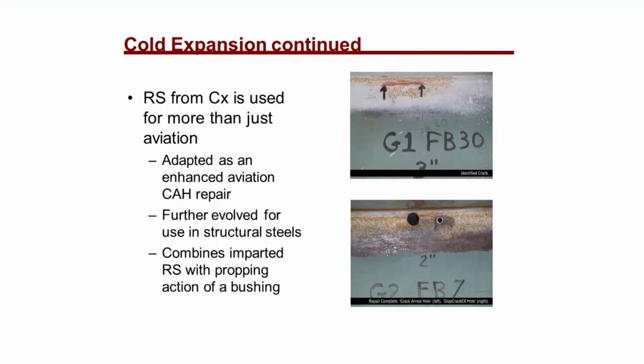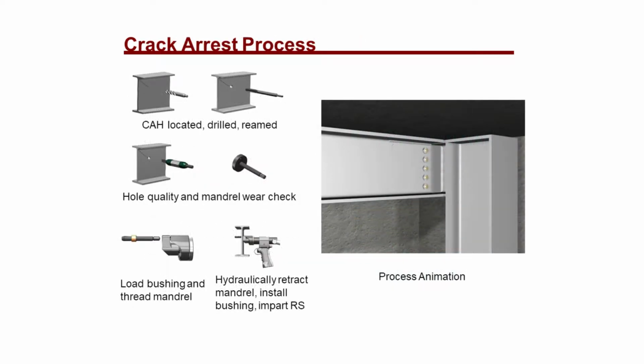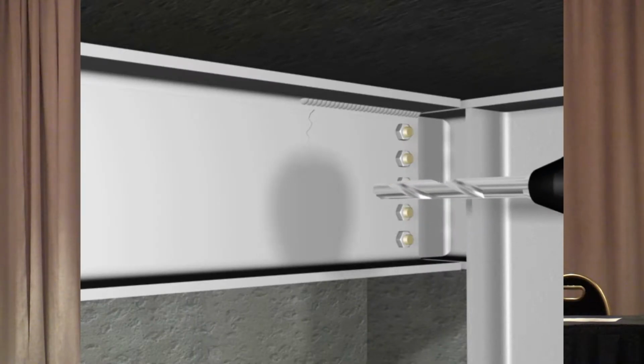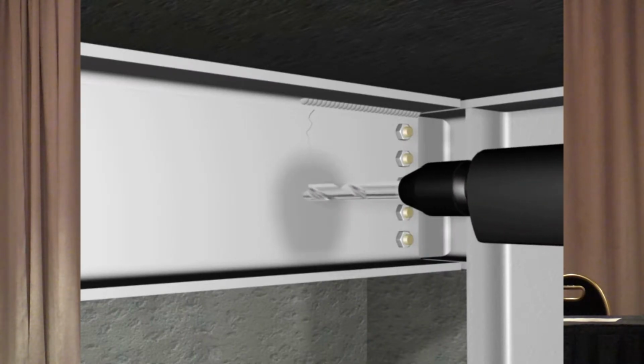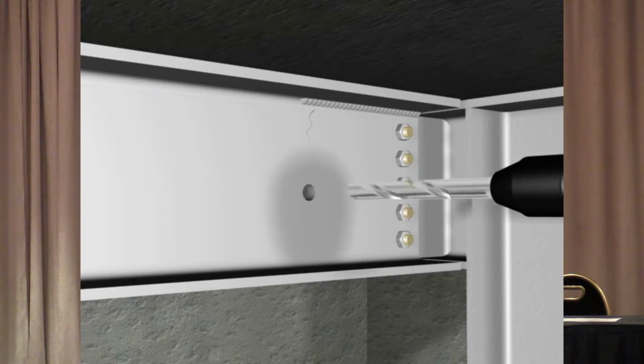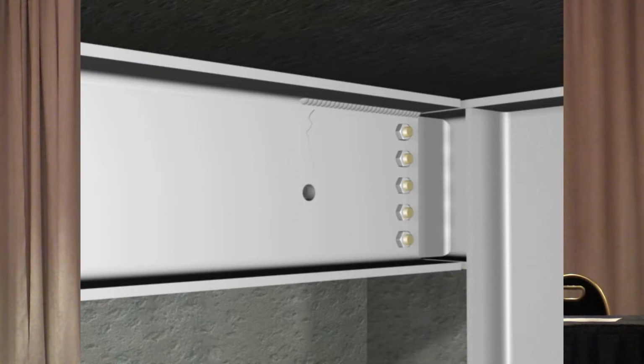Then evolved in the early 2000s for use in structural steels. In structural steels, we're able to further improve that by the action of a bushing that props open that hole. So here's the crack arrest process. It's very, very similar to what you just saw for the cold expansion process. The most important thing is finding that crack tip, and I'm pretty sure that your bridge crews are already pretty good at that. So once you've found the crack tip, we put a very precisely shaped hole in front of it. We want to lead that crack by a 1/16 of an inch ligament.